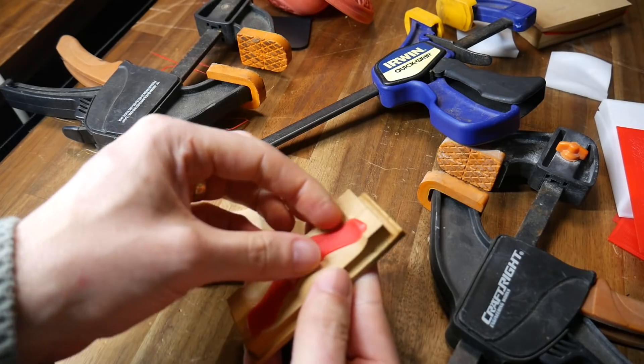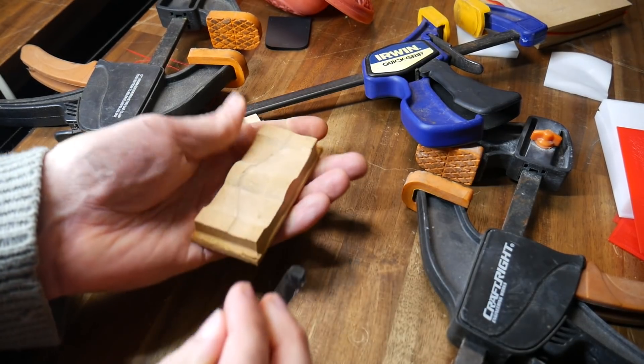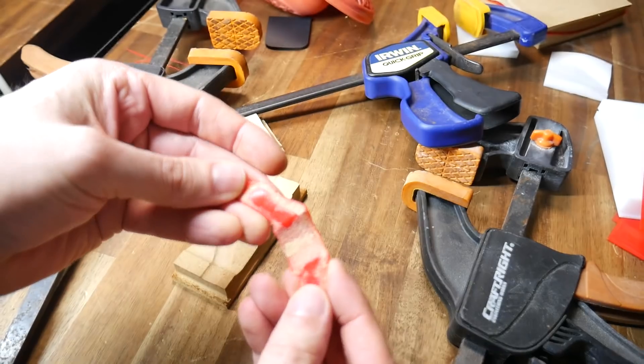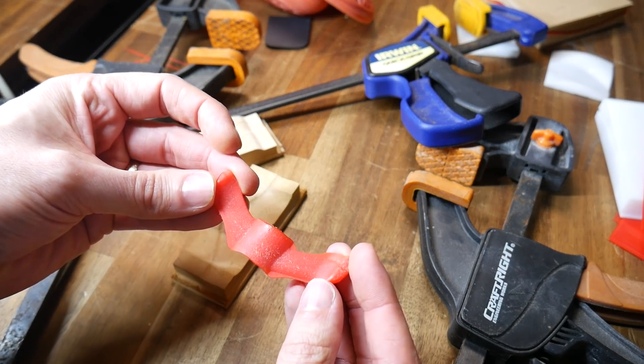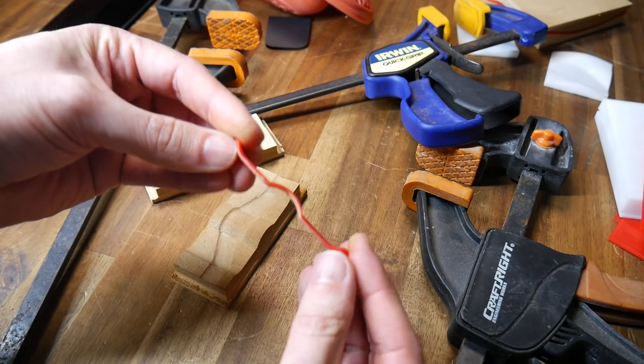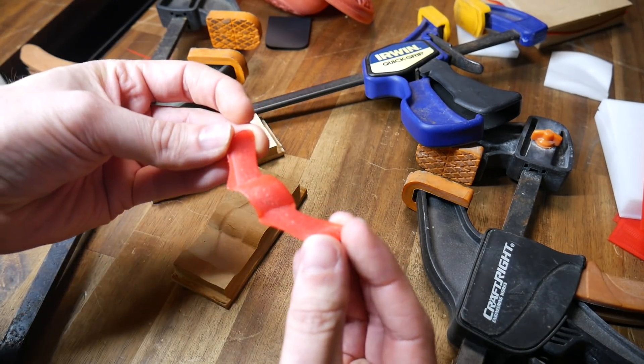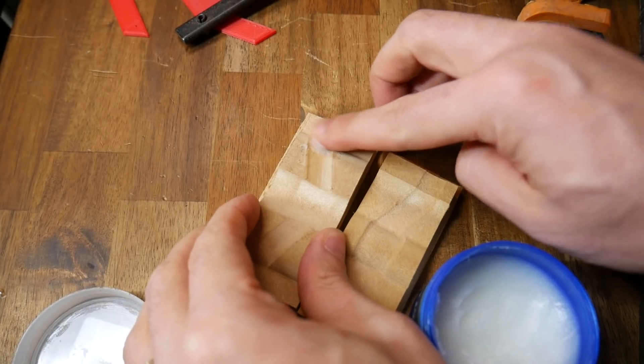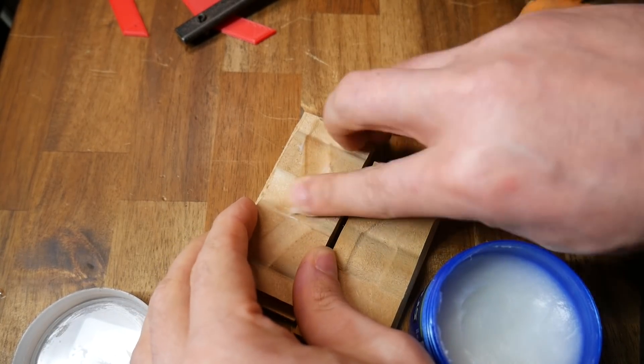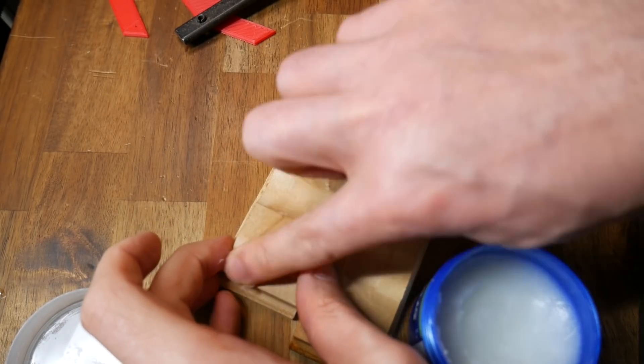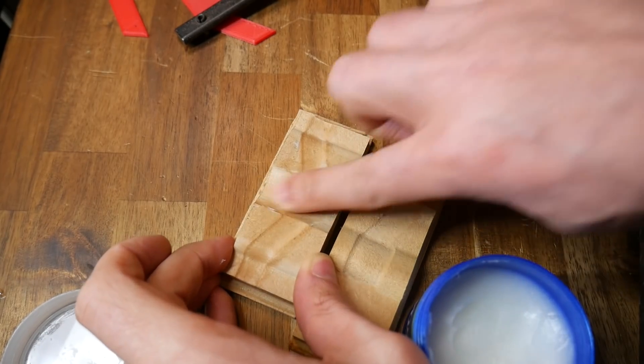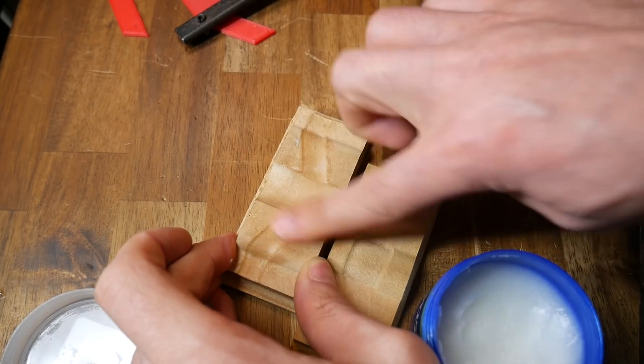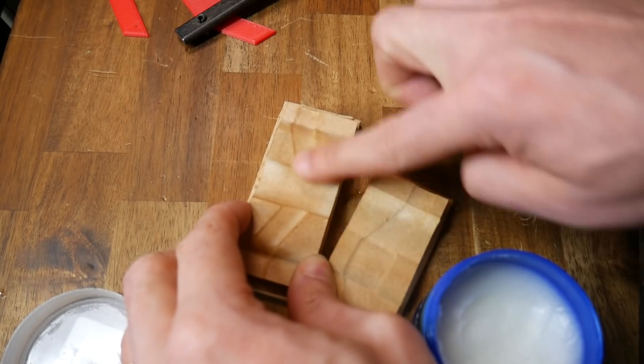After everything cools, we can remove the clamps and open it up to reveal the part inside. The general shape is there, but plastic has oozed in between the two halves of the mold, and we call this effect flashing. Because I didn't do anything to seal the MDF mold, the plastic was molten enough to penetrate the surface, which was removed when I took the part out of the mold. What I should have done is apply a release agent—in this case, hair wax. This has the job of sealing the surface of the MDF, making it less porous and less likely for the plastic to penetrate. It also forms a slippery layer just to help the plastic release in general.